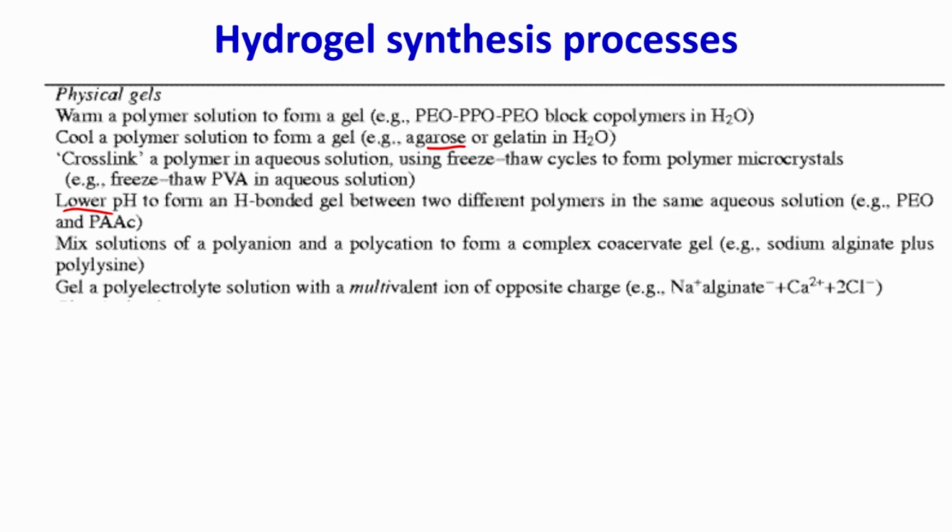Another one that is very widely used is the alginate gels. What is done is sodium alginate, which does not form cross links because it is only a monovalent cation. But then if you drop it into a solution containing calcium, what will happen? Let us say I have a beaker that contains calcium 2 plus, and I make a drop of the sodium alginate and let it drop. The sodium will leave the system and calcium will go in because it has higher affinity, it has a 2 plus positive charge, and so this drop will immediately polymerize to form a hydrogel of alginate. So, that is another way you can form these physical gels.